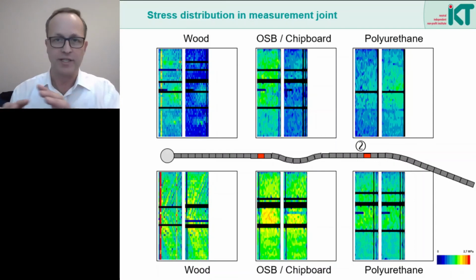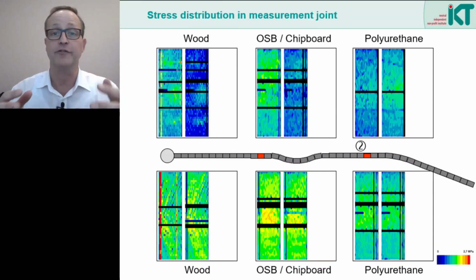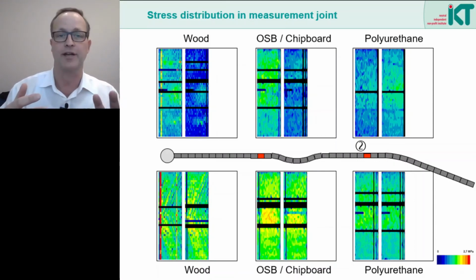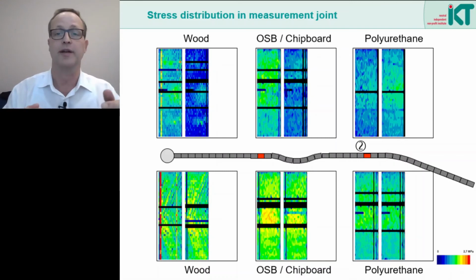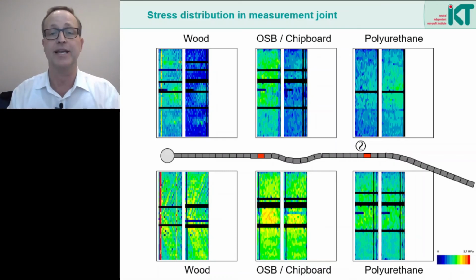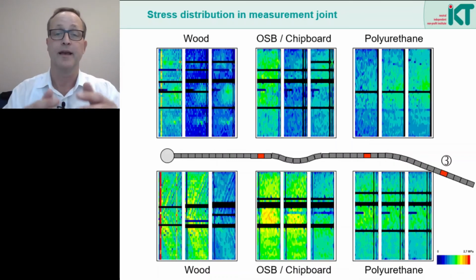In the subsequent straight line, the stresses are then transferred more strongly over the other areas of the pipe joint, over those areas that have not yet been plasticized and still act with elastic behavior. And here we see the results at point 3. That means after passing the second curve, the planned curve. In the following straight line, the stresses in the polyurethane are still the same. The material has again behaved elastically.